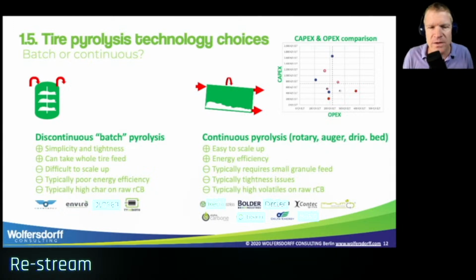Typically also, we talked about the char. Typically, the batch kiln is producing higher char or carbonaceous residue on the raw recovered carbon black. Now, in our case, for the coloring application, that could be a good thing. That could be a bonus. But it is different in continuous kilns. Continuous pyrolysis kilns could be rotary kilns. On the simple side, could be auger kilns.